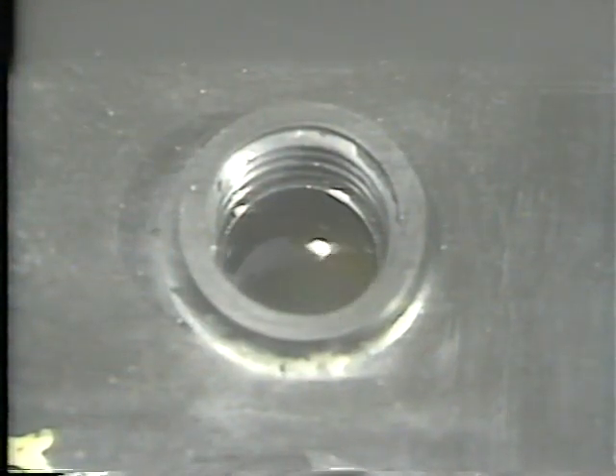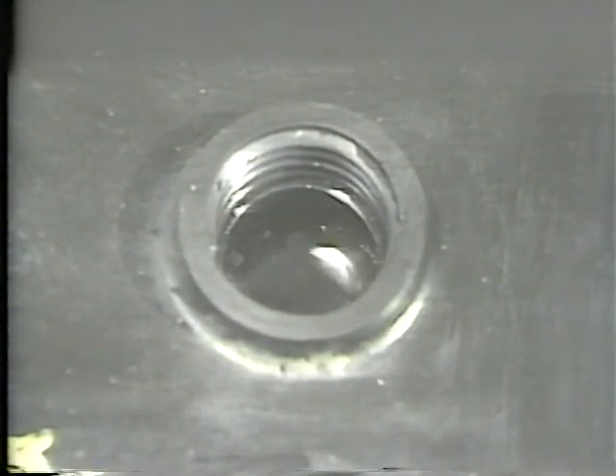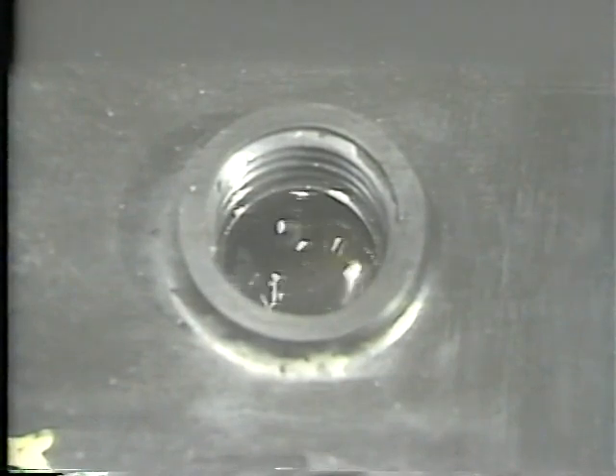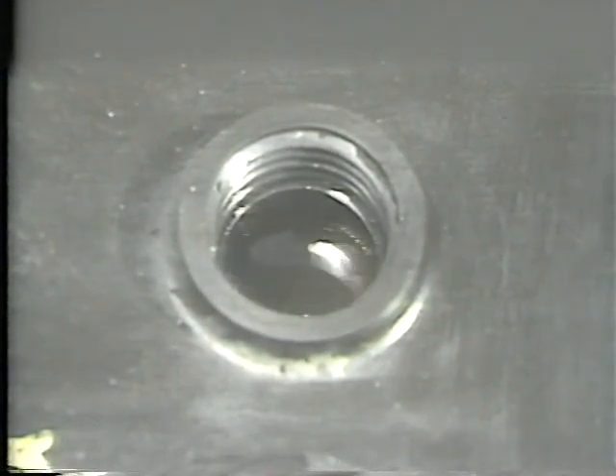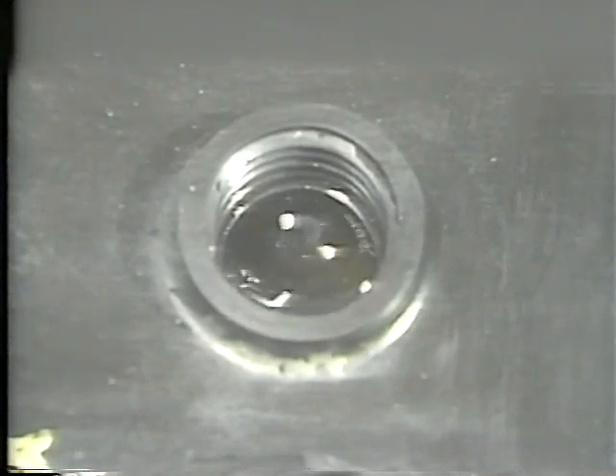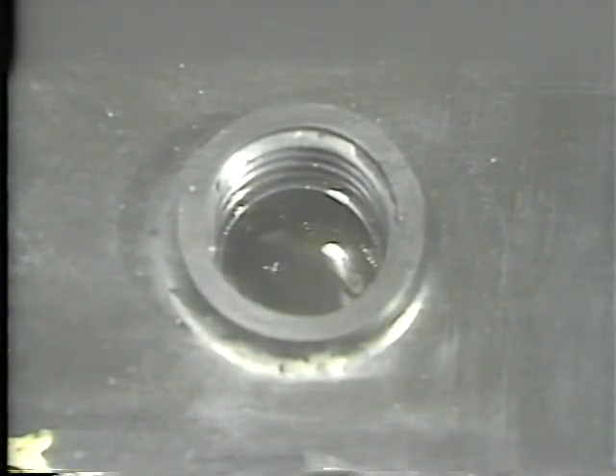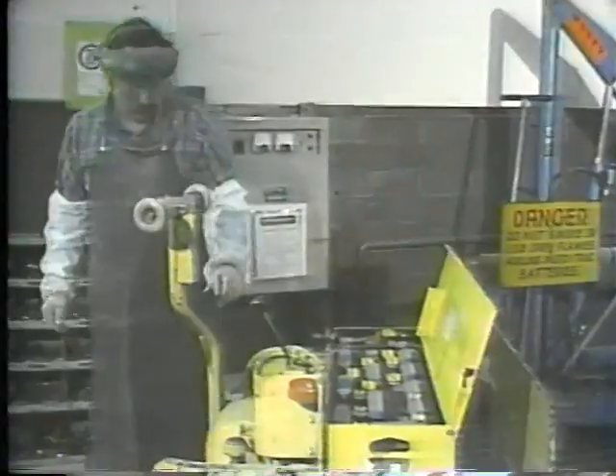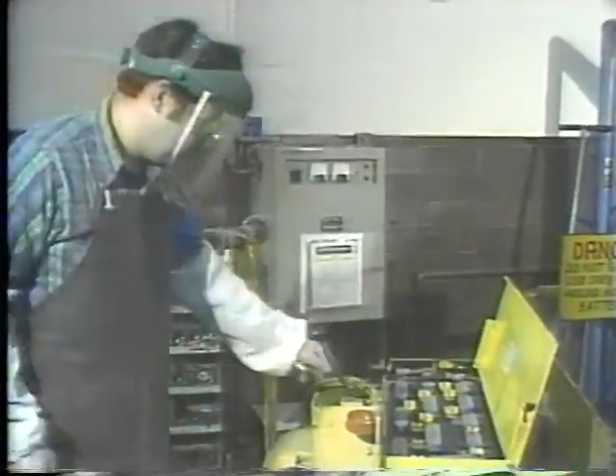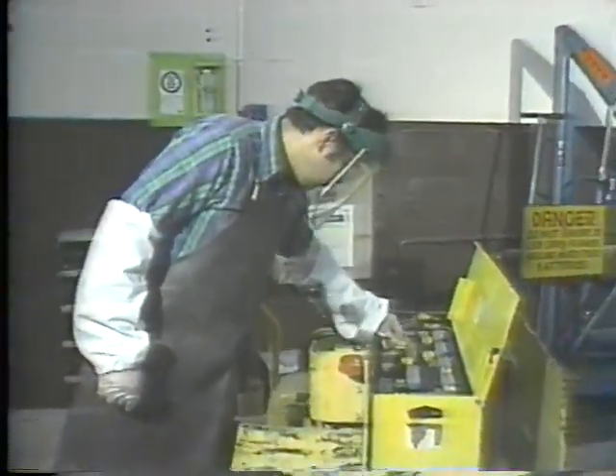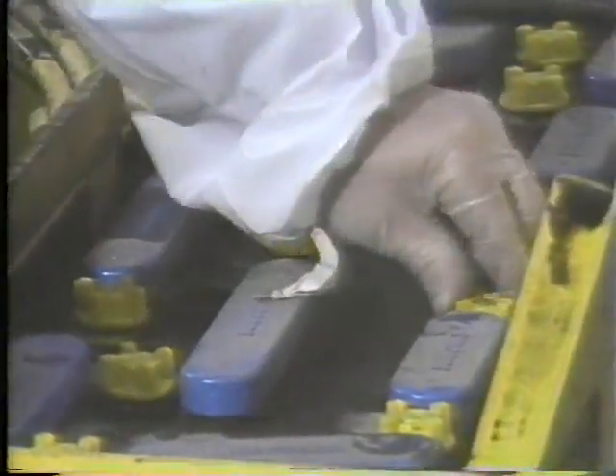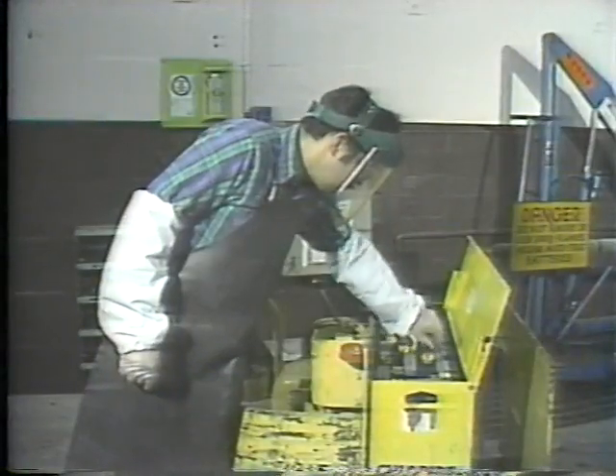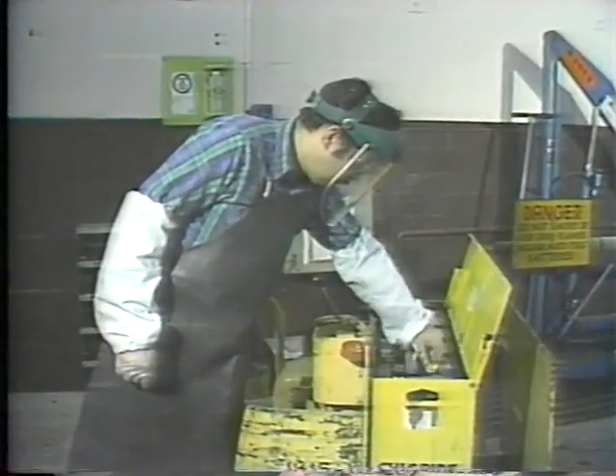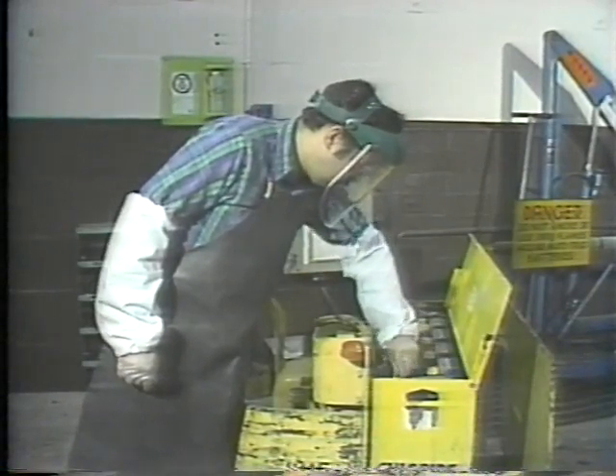With this vent cap removed, you can see the gas bubbles generated inside the cell. This normal amount of gassing won't hurt the battery, but hydrogen gas is flammable, so you don't want to be smoking or creating any sparks or open flames around a battery. If a cell was gassing violently, that would be a sign that the charging rate was too high. Violent gassing can knock the active material off the plates, so you'd have to reduce current flow to slow down the gassing.